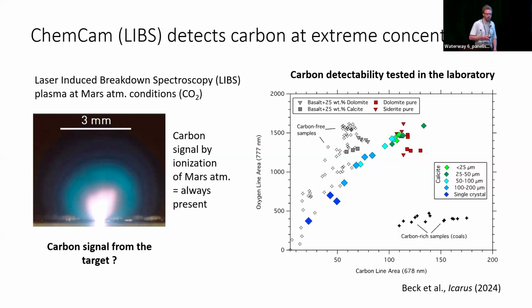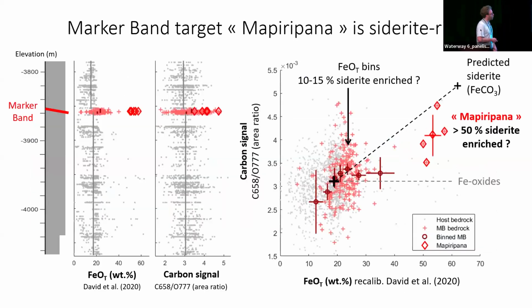What came out of that paper is that if you see a carbon signal from a carbonate that is mixed in a silicate, it means that there is at least 50% by weight of carbonate, tested for calcium, magnesium, and iron carbonates here. So we applied this methodology to the data. When that paper was published, we hadn't gone to the marker band yet, so the paper said we didn't detect any carbonate, but then we arrived at the marker band, and this is how the data plots.